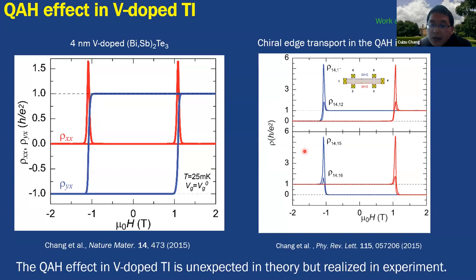And later, I moved to MIT for my postdoc, in collaboration with Moses Chan at Penn State. We realized the second quantum anomalous Hall system, in the vanadium-doped bismuth antimony telluride. This is actually quite a similar system. It just changed the doping.